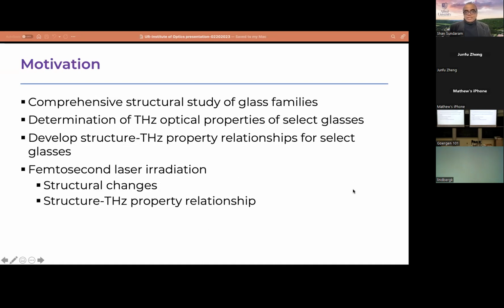Back to the motivation. We were looking at the literature 5 years ago. We found a few results reported on terahertz properties of common commercial glasses. So we thought we would try to locate, is there a comprehensive study out there, particularly on silicate glasses? These are common glasses, soda lime silicate, borosilicate. We could not find any full comprehensive study tying it to the glass structure. So we thought we will start our own, and we will measure terahertz optical properties.